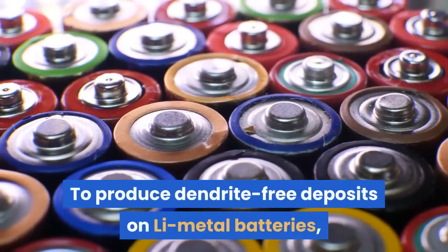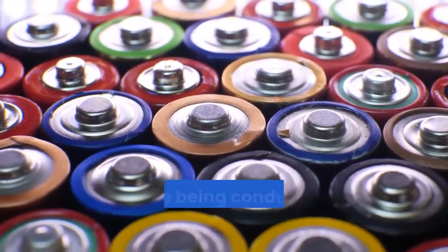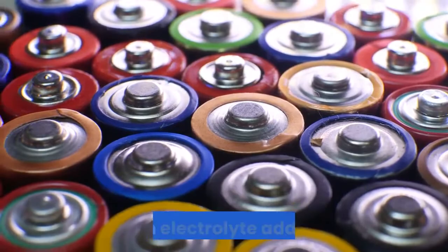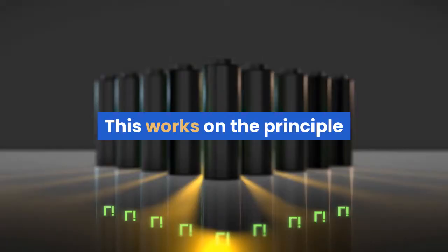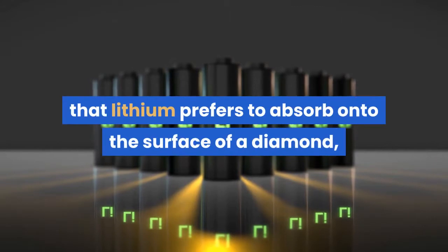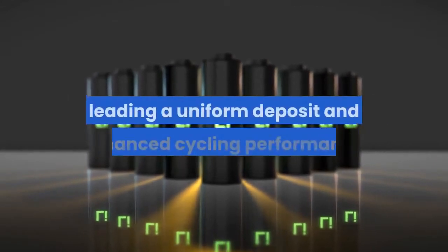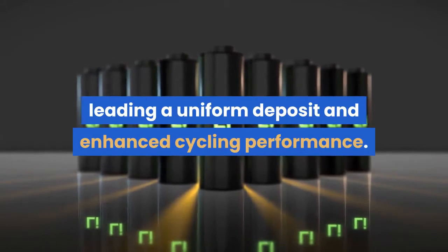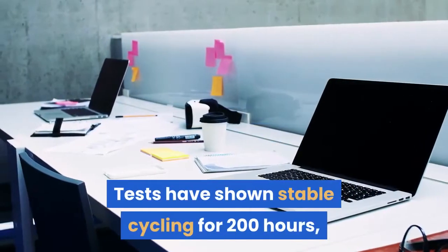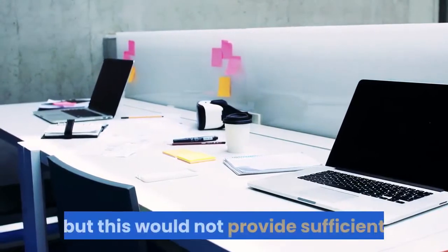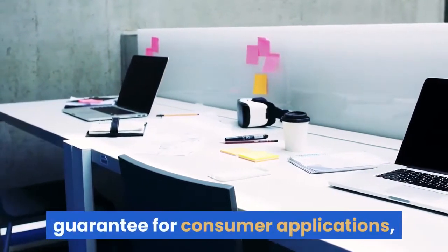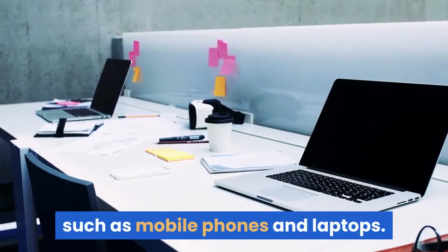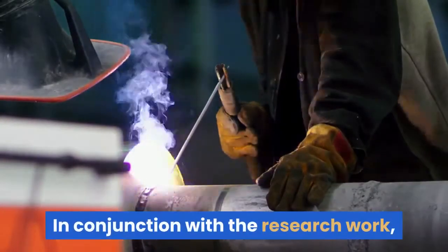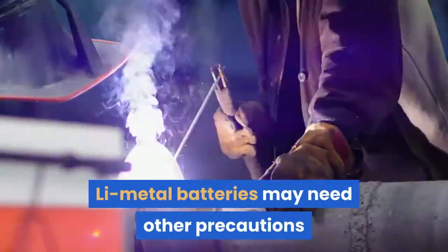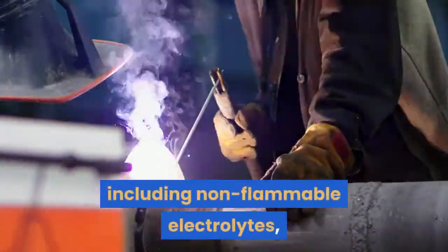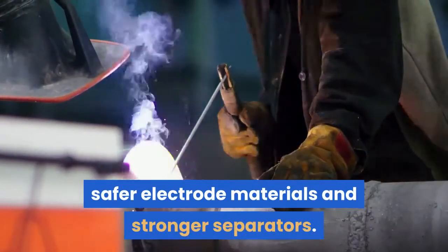To produce dendrite-free deposits on Li-metal batteries, tests are being conducted by adding nanodiamonds as an electrolyte additive. This works on the principle that lithium prefers to adsorb onto the surface of a diamond, leading to a uniform deposit and enhanced cycling performance. Tests have shown stable cycling for 200 hours, but this would not provide sufficient guarantee for consumer applications, such as mobile phones and laptops. In conjunction with the research work, Li-metal batteries may need other precautions including non-flammable electrolytes, safer electrode materials and stronger separators.